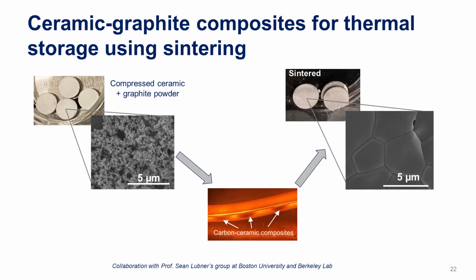And so here's some images of compressed ceramic with graphite powder. We work a lot with alumina as our ceramic and mixed in with graphite. We choose the amount of graphite in that composite so that we're getting electrical percolation and thermal percolation through the composite. And then what we do is we sinter it.